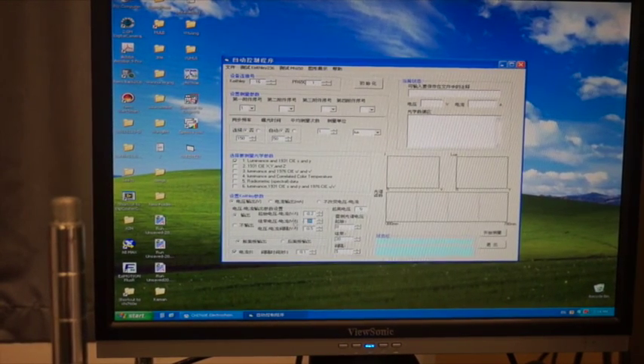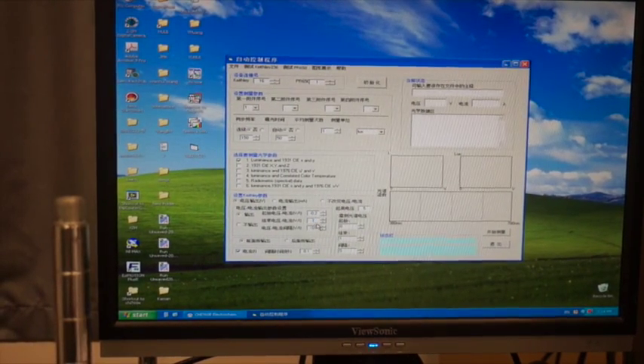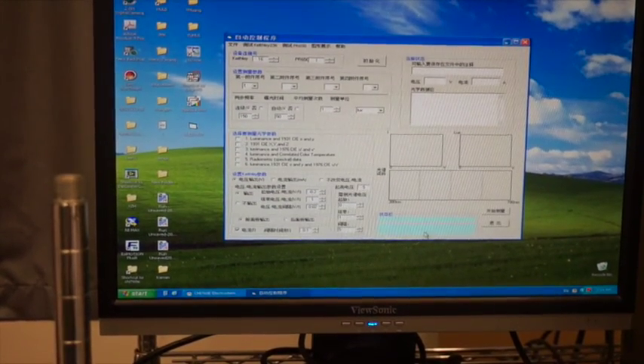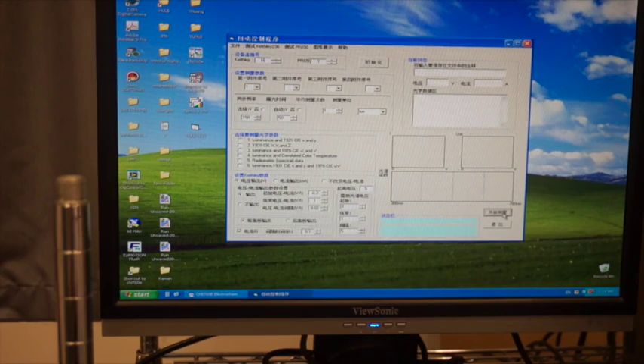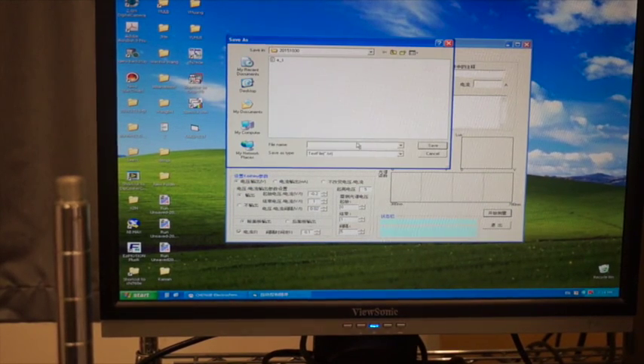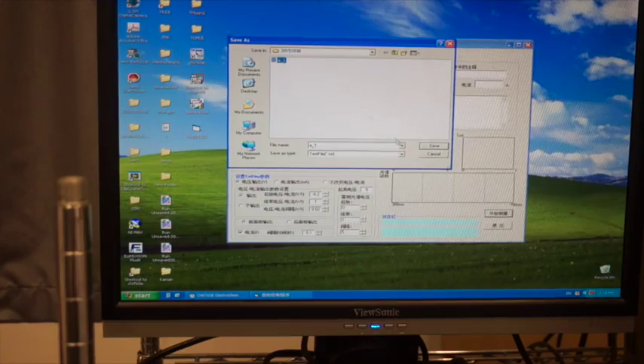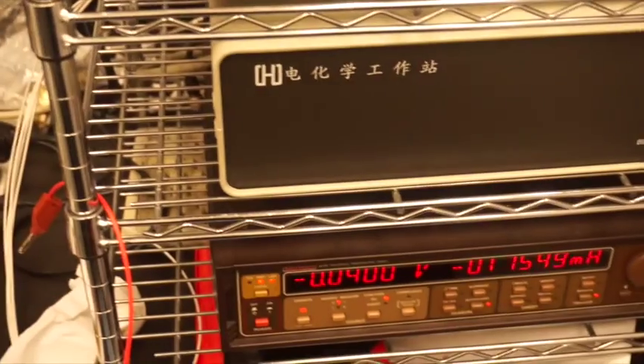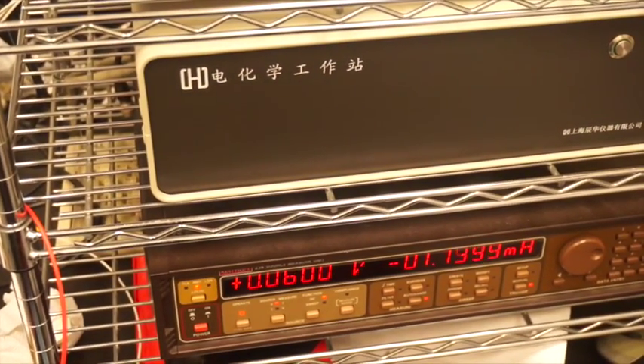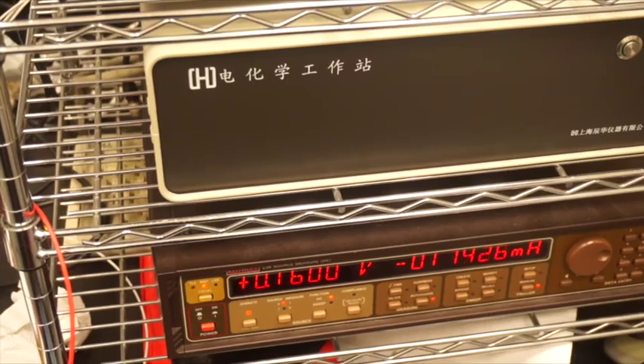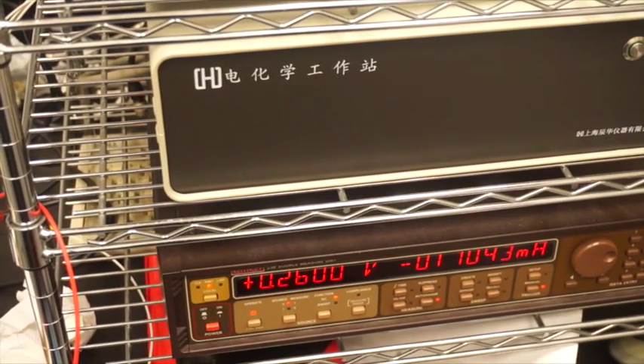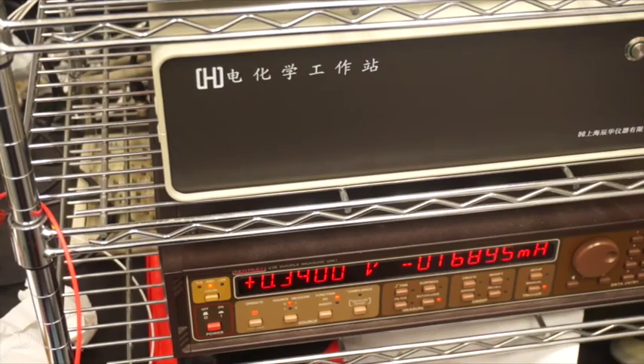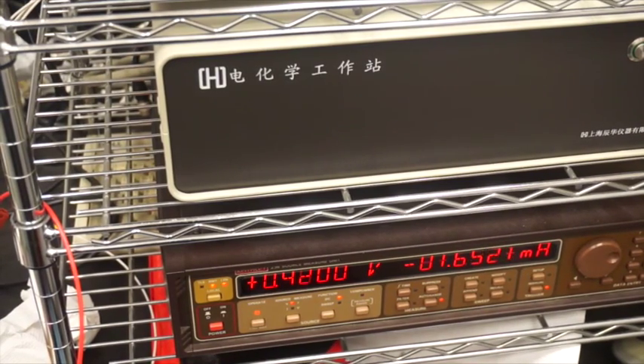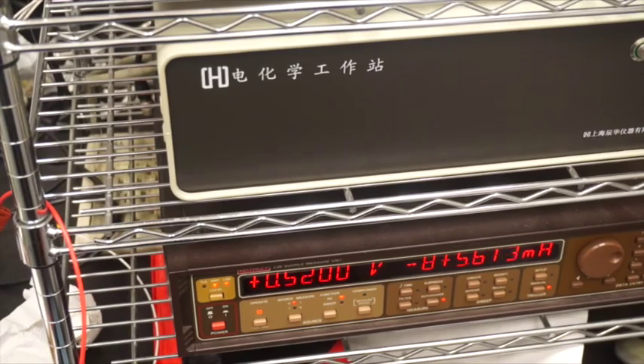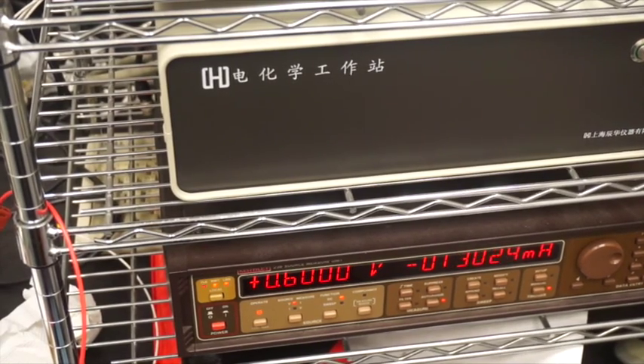Measuring solar cell performance is done by scanning an applied voltage across the solar cell and measuring the current response of the solar cell. Then we will get a curve, which is the current plotted against the applied voltage. So here we start the scan. As you can see, the current is relatively unchanged at the initial stage, and then the current starts to fall very rapidly.